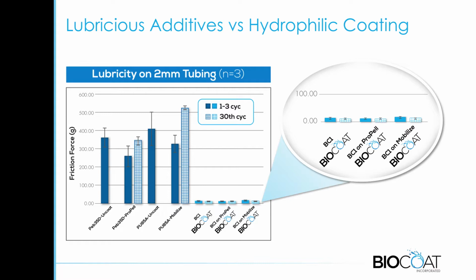And then the other part is putting a hydrophilic coating on top of them. Taking a look at all of these on these 2mm tubings, you can see that both of these additives do reduce the friction somewhat from the unmodified ones, by about 25%.